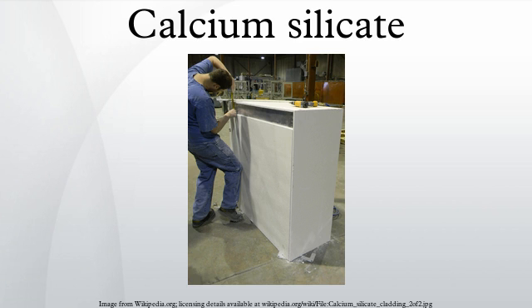Acid mine drainage remediation: Calcium silicate, also known as slag, is produced when molten iron is made from iron ore, silicon dioxide, and calcium carbonate in a blast furnace. When this material is processed into a highly refined, repurposed calcium silicate aggregate, it is used in the remediation of acid mine drainage on active and passive mine sites. Calcium silicate neutralizes active acidity in AMD systems by removing free hydrogen ions from the bulk solution, thereby increasing pH. As its silicate anion captures H+ ions, it forms monosilicic acid, a neutral solute. Monosilicic acid remains in the bulk solution to play other important roles in correcting the adverse effects of acidic conditions. As opposed to limestone, calcium silicate effectively precipitates heavy metals and does not armor over, prolonging its effectiveness in AMD systems.